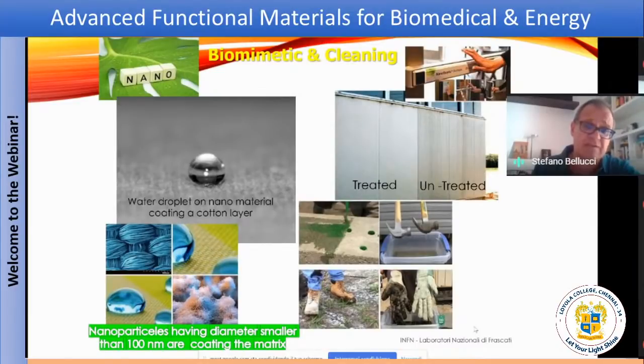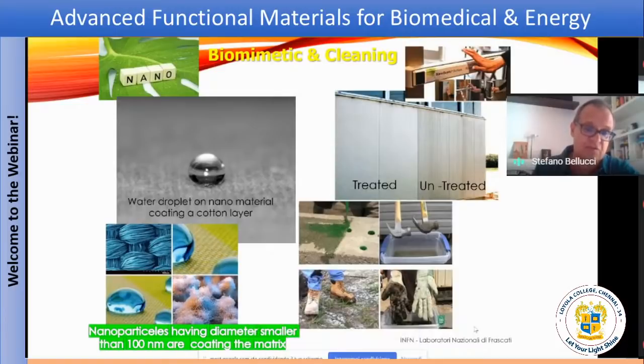On the left-hand side, you also see another interesting feature that is called biomimetic, because it just imitates nature. It is the so-called lotus effect. The lotus leaf doesn't let water absorb on it, and here there's a cotton layer that has been coated with a nano coating. This nano coating is based on titanium dioxide, and it doesn't allow any droplet of liquid to stain or to wet the surface. So you have different applications in textiles.